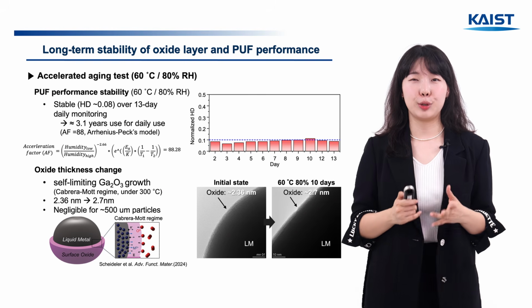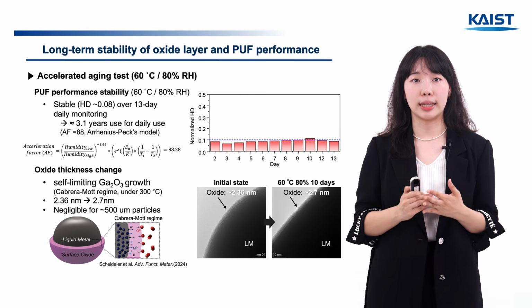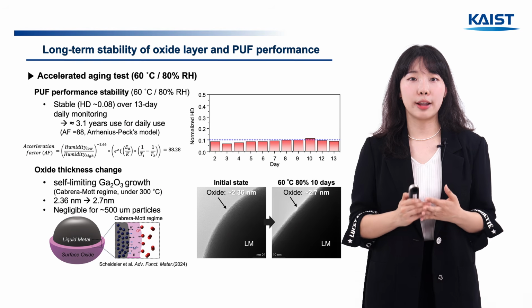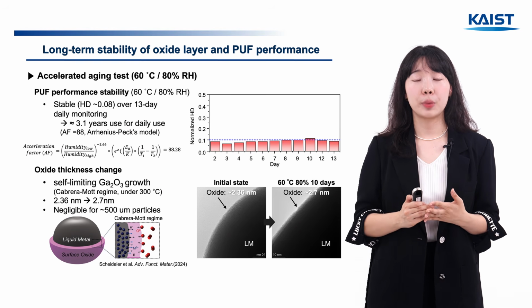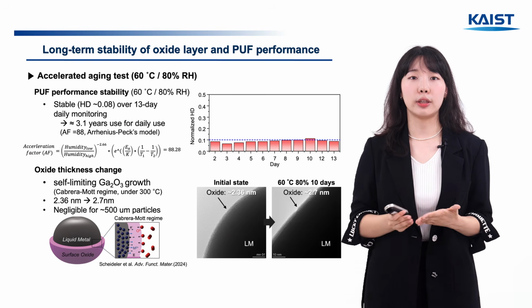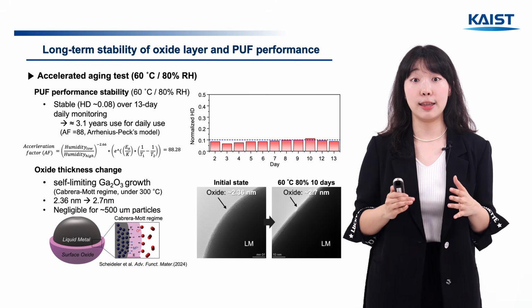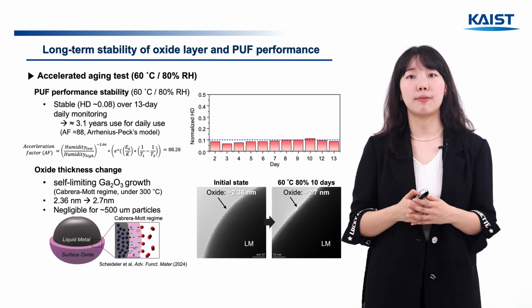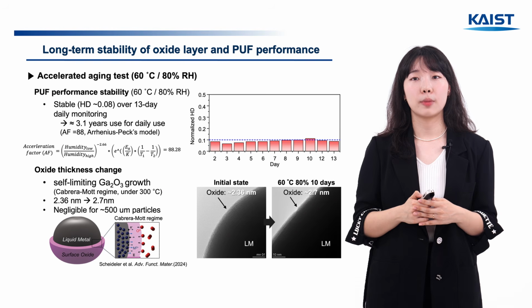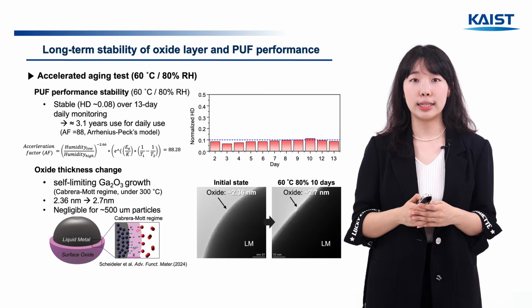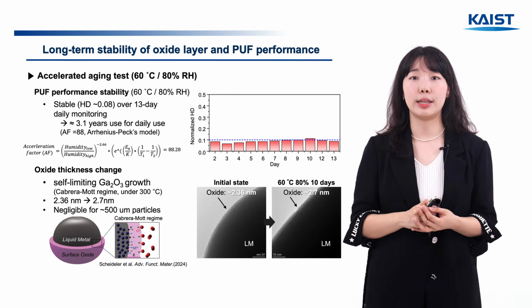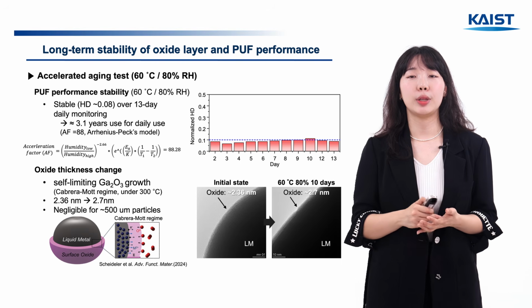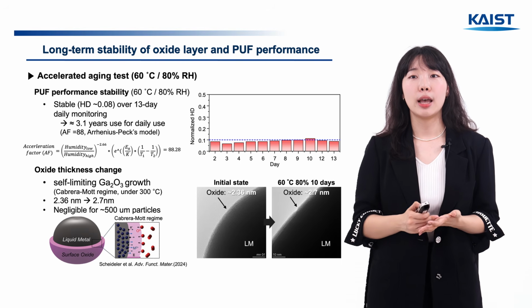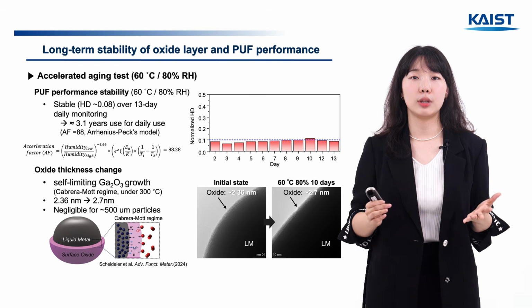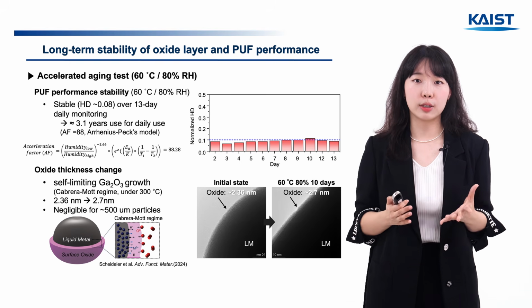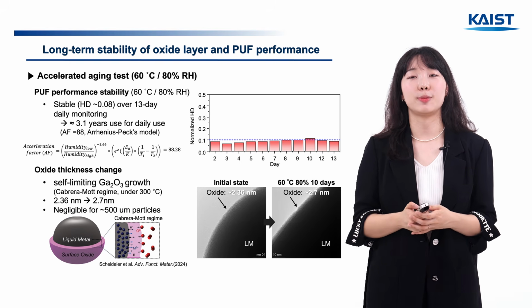I think this is due to the self-limiting effect of the oxide layer. Based on the Cabrera-Mott oxidation theory, the native gallium oxide is electrically insulating, so it inhibits further oxide growth by limiting electron tunneling. So in fact, even after 10 days at 60 degrees and 80% humidity, it grew by only 0.34 nanometers, and for a PUF particle that's around 500 micrometers, a change this small is negligible.